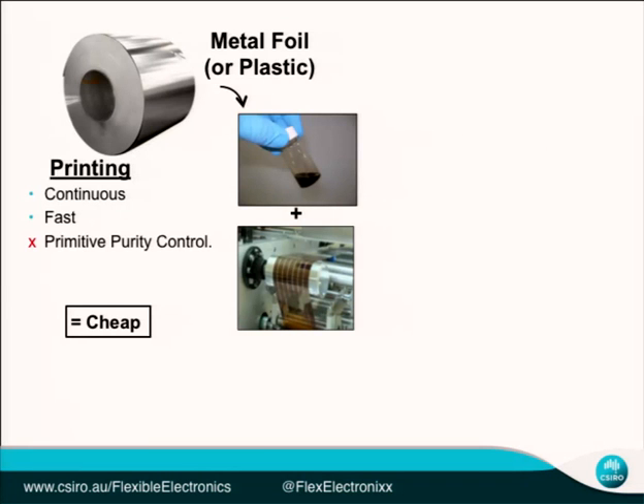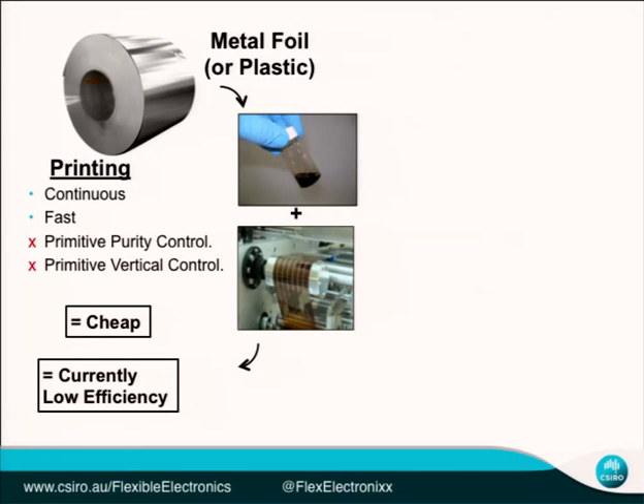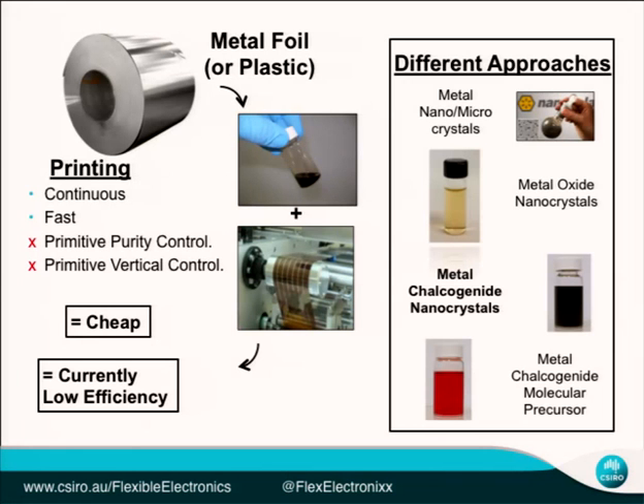But at the moment, we have pretty primitive control over the purity of the materials or of the vertical structure of these devices. So a way to address this, to enhance the problems that we have about low efficiency, is to use these nanoparticles. There are a few different approaches to using nanoparticles, and you can either make them in solution or make precursors to them. But what Jack and Brandon developed was a process where we could take these nanoparticles in ink and deposit them down in a film to make a solar cell. So all from solution, all in air.